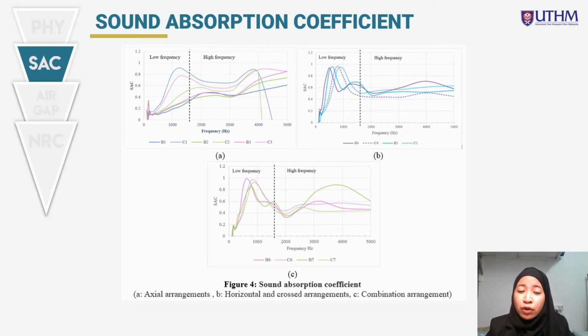This is probably because the samples are too packed, which deteriorates the acoustic absorption performance at a certain point. The absorption performance of a material is higher for denser materials due to an increased frictional surface between the acoustic wave and the fibers. At a certain limit, the frictional effect between the acoustic wave and fibers is less, since it is difficult for the acoustic wave to penetrate a material with fewer pores.